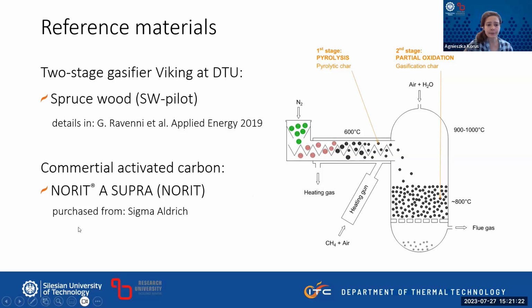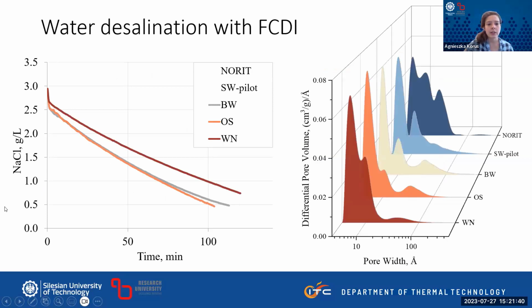And as the reference for the commercial carbons, we used Norit Supra from Sigma Aldrich, which has been commonly used for FCDI purposes as well. So we just wanted a reference to see how the biochar works compared with the commercial products. And here you can see some tests from the saline water desalination. You can see the decrease in the salt concentration with time as the process was going on.